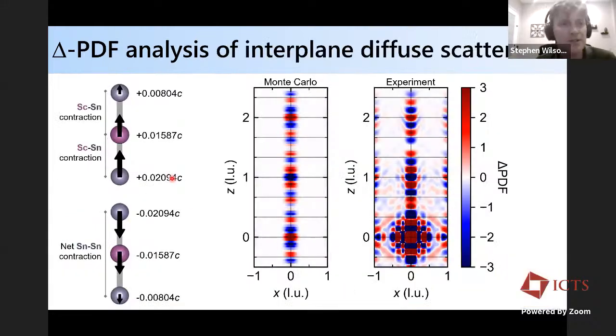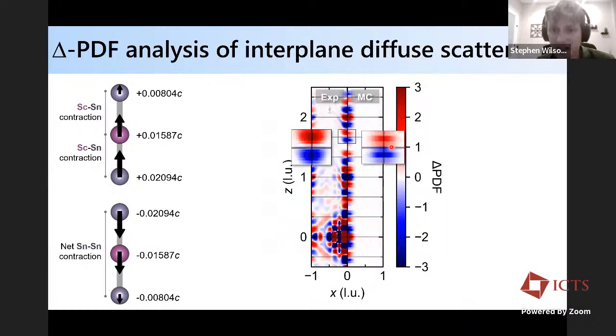Okay, so the first thing we wanted to do is look at the motion of these trimers. You can assume the low temperature trimer state and displacement, and then do a Monte Carlo type of model where you fix this but allow the trimer to displace up and down, and see if that can capture the delta PDF pattern that you see from the experimental, transformed data. And indeed it does. So by using this out-of-plane data, one can map and show that indeed you have these trimer units in the high temperature phase. Okay, so the ones that exist at low temperature are also fluctuating at high temperature.